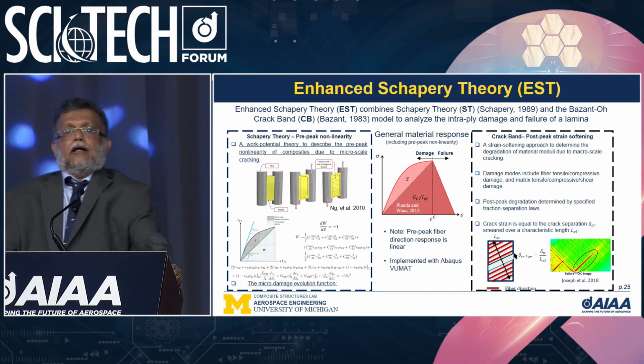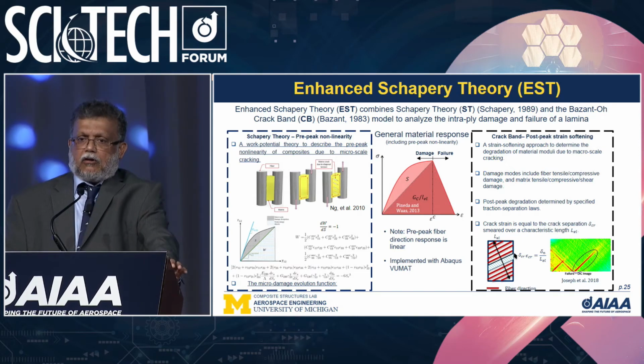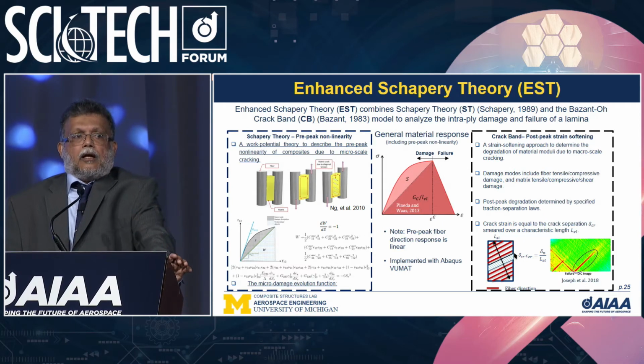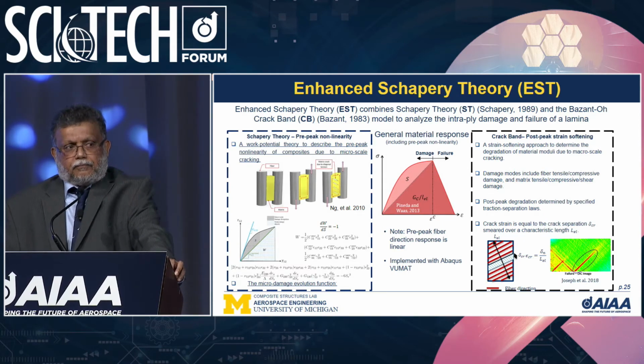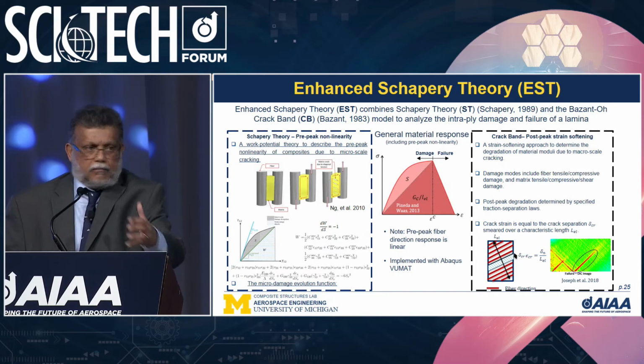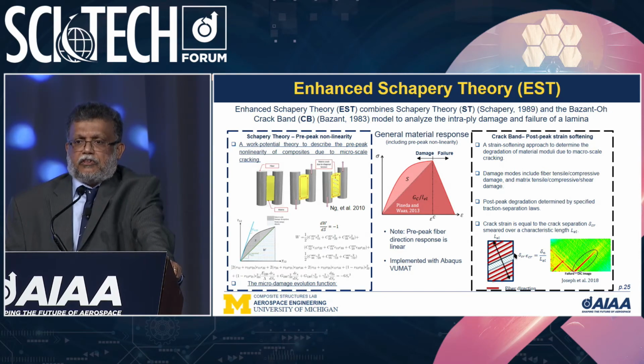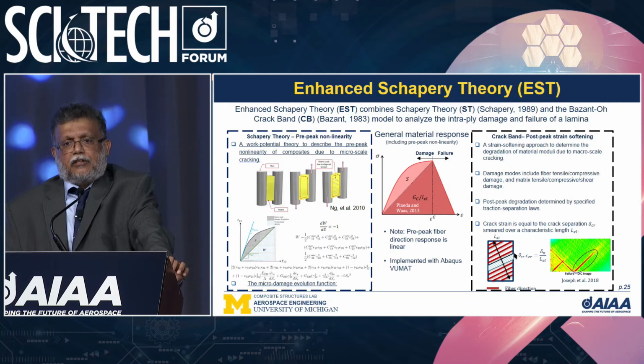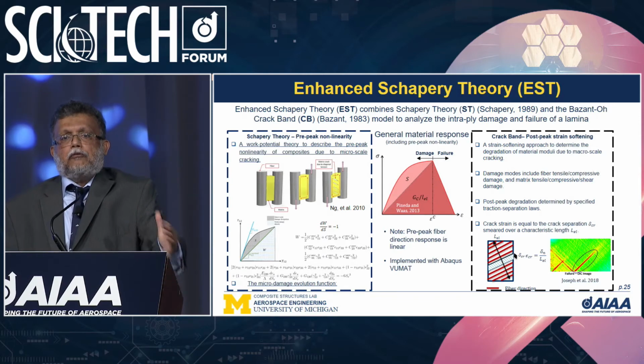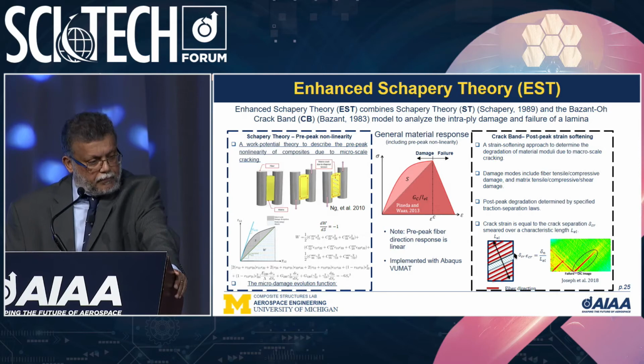So EST is a pre-peak nonlinear model for the matrix, embedded with the crack band method, and that's coded up in any commercial finite element code via a subroutine implementing these features. In addition, we developed the I2CBM code at Michigan, which has an added feature allowing you to put in crack spacing based on shear lag theory—calculated outside the code and input as a crack tracking algorithm. That was the thesis of one of my students, Ashit Joseph.